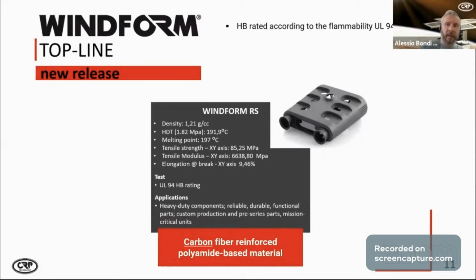Last born of the family is Windform RS. That's a very strong one. It's with a density of 1.21. You can see a very, very good HDT for a polyamide, for a polymer. Okay, it's carbon fiber reinforced. It's 191 degrees Celsius and 197 as a melting point. Look at the tensile strength, it's 85 megapascal and the tensile modulus is 6,638 megapascal. And with an elongation at break, so it's not bad, it's 9.46%. This one is very good for heavy duty applications.